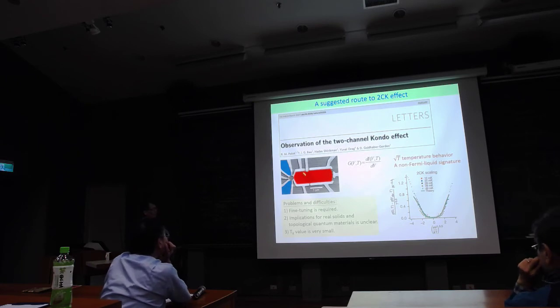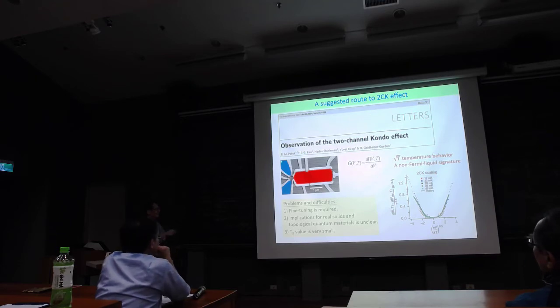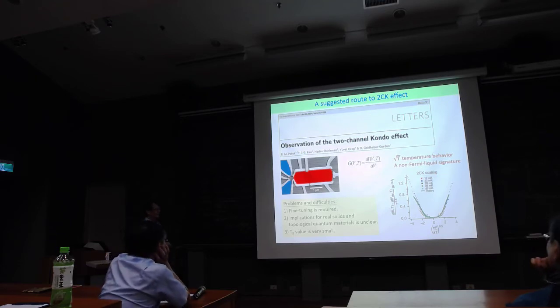But in this case, you can see that there is a lot of back gating, top gating, and a lot of source spread. So you need a lot of fine-tuning. It's very, very difficult. And so far, this may be the only report. Already more than 10 years, there's no second report yet. And this is quantum dots.